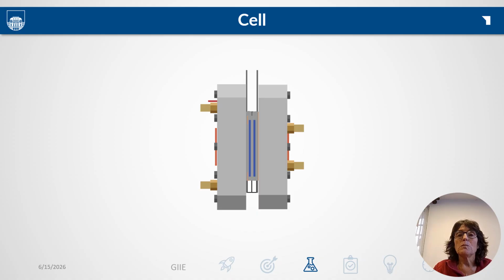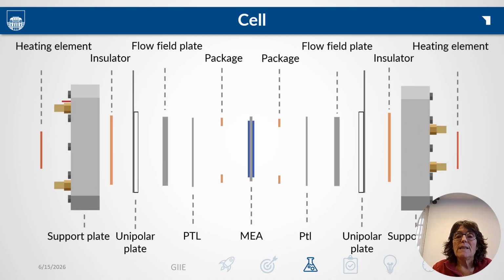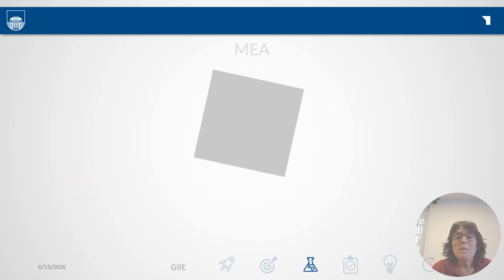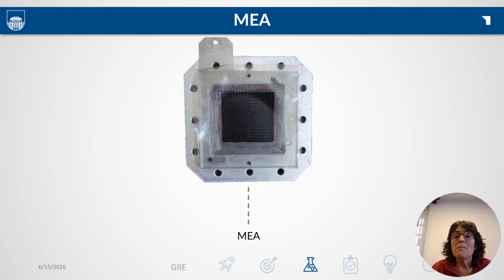The cell exploded view. From the outside inwards, the cell has a heating element, a support plate, an insulator, a unipolar plate, the flow field plate, the porous transport layer, a gasket, and the membrane electrode assembly itself, and the symmetric structure on the cathodic side. The membrane electrode assembly, as I mentioned, is a catalyst coated membrane with a geometric area of 25 square centimeters and a catalyst loading of 3 milligrams per square centimeter per side.